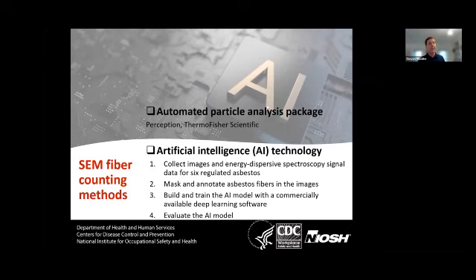And the nice thing about this is we can actually use, and we've started to do this, automated particle analysis packages with the SEM. So we can collect the sample on our filter, put our filter in the SEM, and then have the SEM automatically count the fibers. It'll give us a size distribution, length and width.